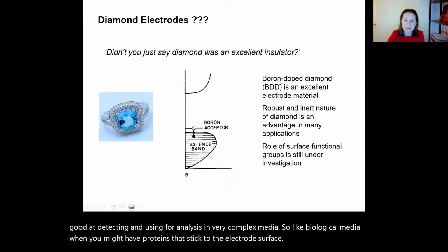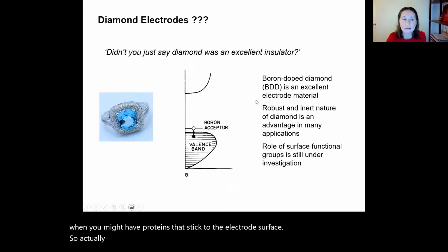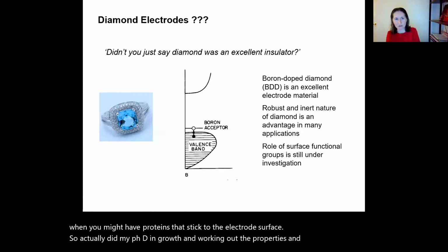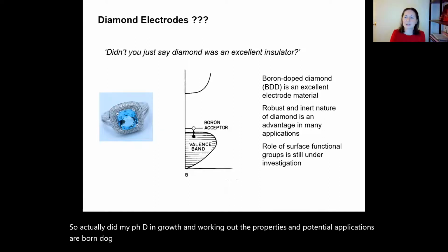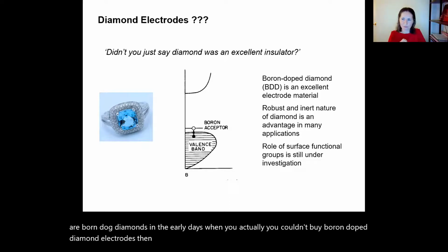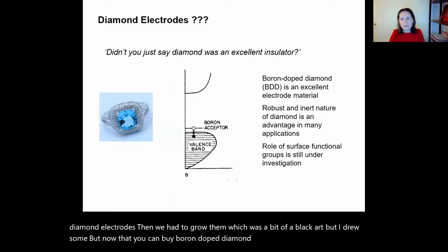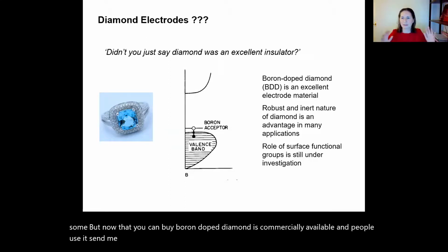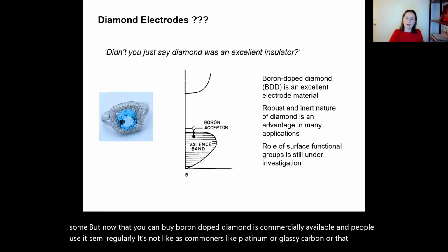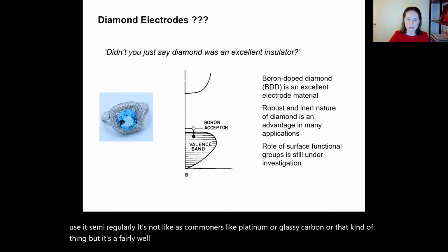So actually I did my PhD in growth and working out the properties and potential applications of boron doped diamonds in the early days, when you couldn't buy boron doped diamond electrodes. Then we had to grow them, which was a bit of a black art, but I grew some. But now you can buy boron doped diamond. It's commercially available and people use it semi-regularly. It's not as common as platinum or glassy carbon, but it's a fairly well-known electrode material these days.